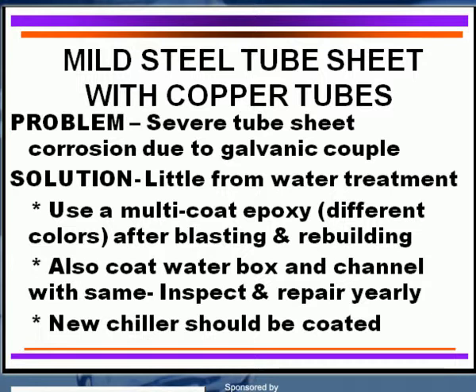What you need to do is go with cleaning and sandblasting, rebuilding the surface, and then applying a multi-coat epoxy on that surface to protect it against the corrosive nature of the water. Why do we use a multi-coat epoxy with different colors? Well, if you use different colors, you can identify any voids that may have occurred on the first coating. I frequently like to have 3 coatings, 3 different layers of 3 different colors, and that works out very well. Be sure you also coat the water box and the channel while you're doing the same thing,